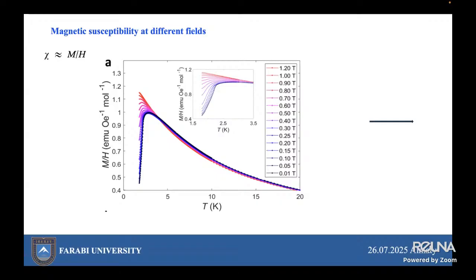And this is a zoomed view of the low temperature region, between 1.5 and 3.5 Kelvin, showing a clear separation of the curves for different fields. At high magnetic fields, the red curves, the maximum of the ratio of magnetization to magnetic field shifts slightly and is less pronounced. These features suggest field-dependent suppression of magnetic ordering and are typical for systems with competing interactions, spin glass behavior, or low dimensional magnetism.